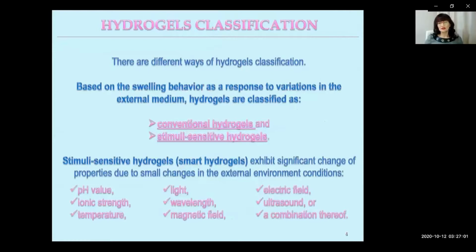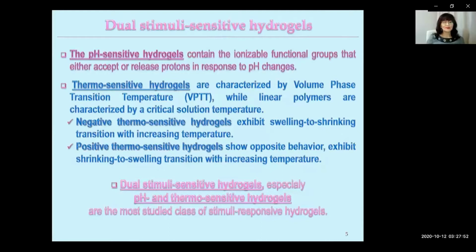There are different ways of hydrogel classifications. Based on the swelling behavior as a response to variation in the external medium, hydrogels are classified as conventional hydrogels, which are not significantly sensitive to changes in the environment, and stimuli-sensitive hydrogels, smart or intelligent, which exhibit significant change of properties due to small changes in the external environmental conditions, such as pH value, ionic strength, temperature, light, wavelength, magnetic or electric field, ultrasound, or a combination thereof. The pH-sensitive hydrogels contain the ionizable functional groups that either accept or release protons in response to environmental pH changes.